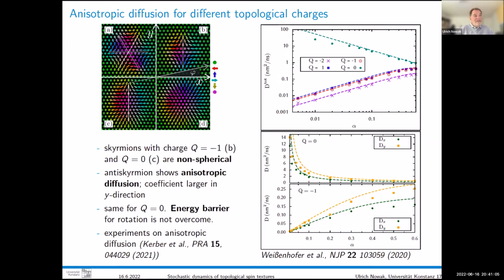The one is some of these structures are not rotationally invariant. So they have a shape, you could say, like this one or that one. You see here's like an axis. It is a bit longer in this direction than the other. That depends on the details of the interaction, right? And if they have a shape, that means that also their diffusive motion is anisotropic. So it's different in the one direction as compared to the other. And that's what we tested here. So Q equals 0 and Q equal -1, they are both not rotationally invariant. And then the diffusion coefficients in X and Y direction are really slightly different. So that's a bit more complicated than here, where that was averaged out. That was published here in this work by my PhD students.